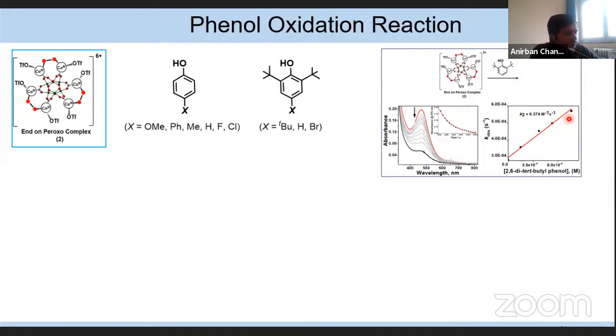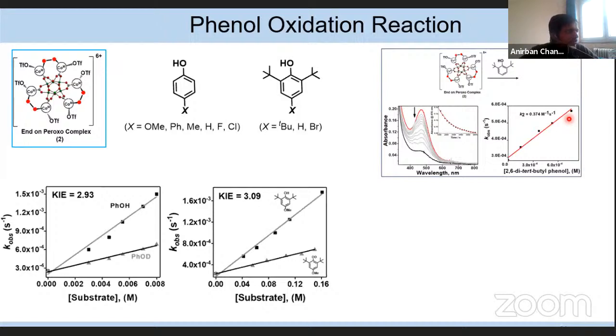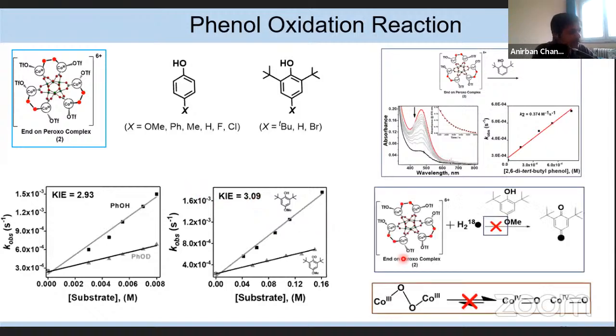Now, to know whether this O-H bond activation takes place at the rate determining step or not, I determined the KIE value using phenol and its deuterated version, and also 4-methoxy-2,6-di-tert-butylphenol and its deuterated version. And we see that the KIE values are almost similar, around 2.93 and 3.09, and such a low KIE value we already observed during the electrophilic oxidation reaction.